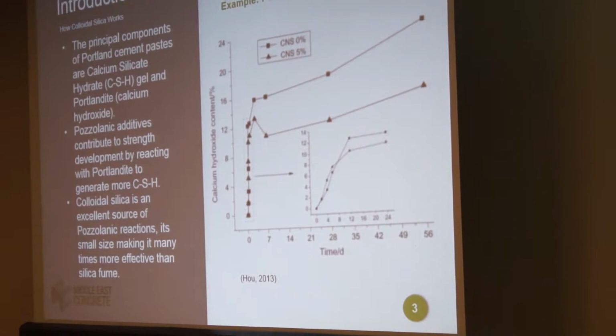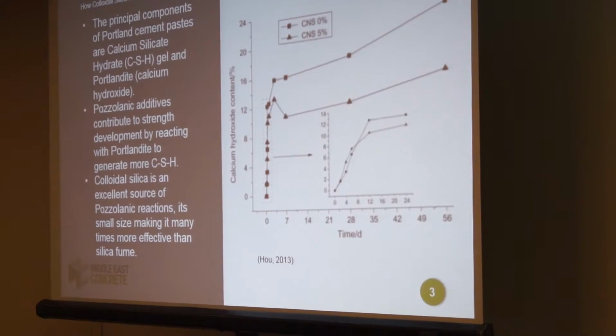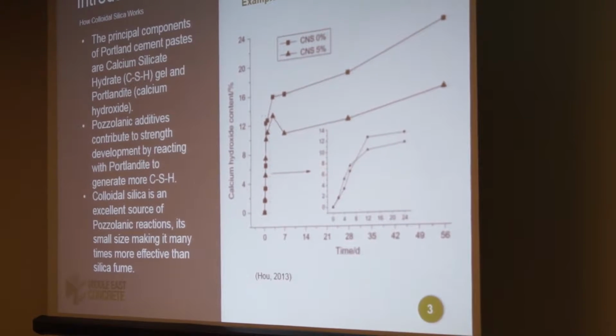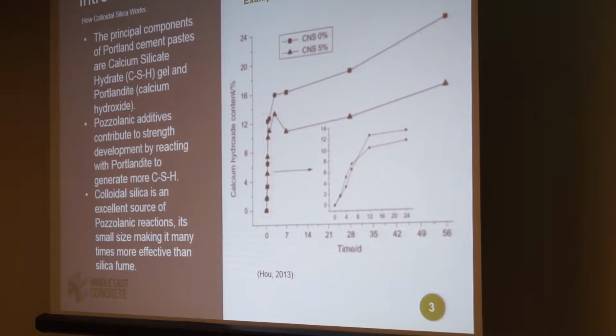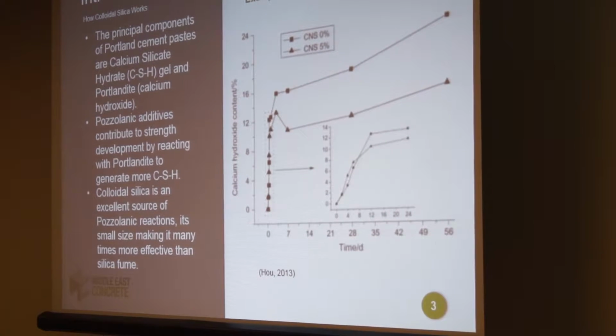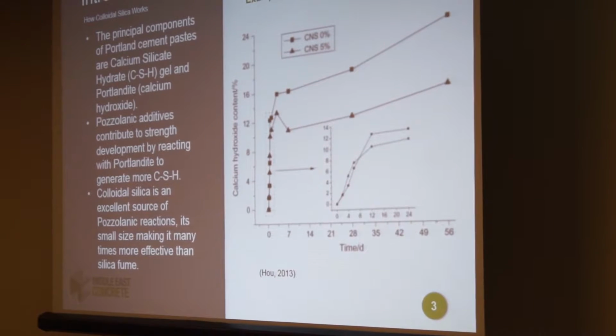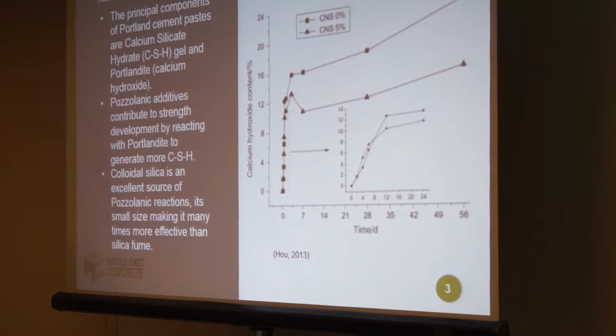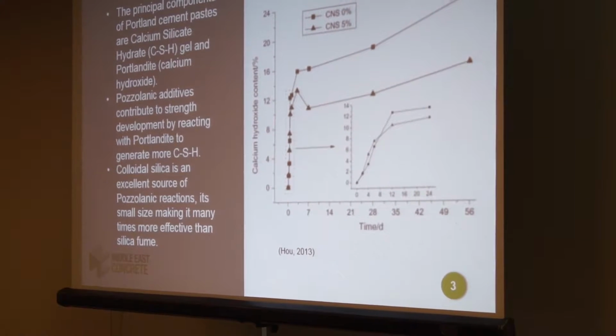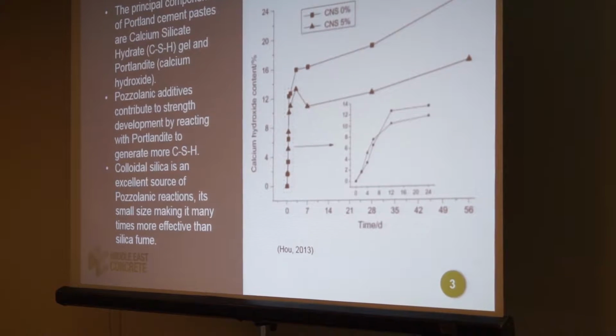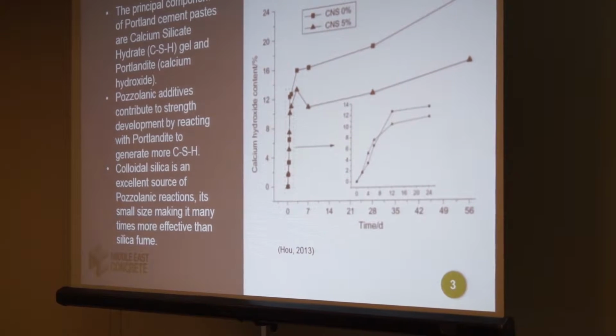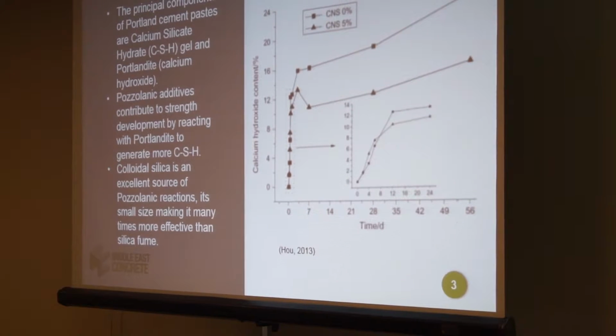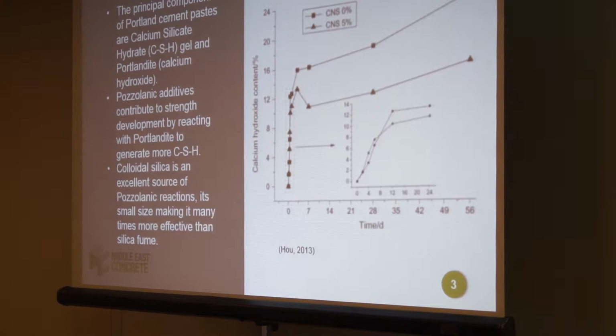The way they work in general, this is just a brief overview, is that they react in a way that is very similar to the traditional pozzolanic reaction, which many of you, if you've studied concrete, know what that is. It's where a silicon-bearing material reacts with existing calcium hydroxide to form more calcium silicate hydrate. Calcium silicate hydrate is one of the 4 main reaction products of the cement and water hydration reaction. So this secondary formation of calcium silicate hydrate can happen later.